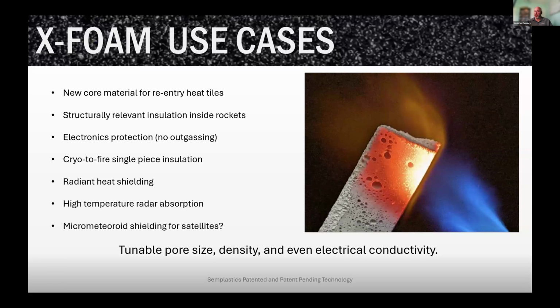And then one of the other really interesting things, we can tune the porosity, thus the density, to a very tiny 50 micron pores all the way up to millimeter sized pores. We can also change the electrical conductivity of this material from extremely insulating to very conductive, which means that it can be radar absorbing. And so it can be a radar absorbing, heat insulating material that is very stiff and machinable and extremely light, 1/7 the weight of water.